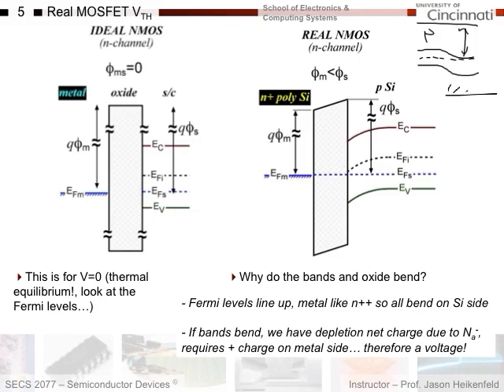if this is the vacuum level up here, and I have n-type semiconductor and then p-type semiconductor, you can see that the distance between the vacuum level and the n-type semiconductor for work function is less than the distance for p-type semiconductor and the vacuum level. So phi sub m is less than phi sub s because the metal in this case is heavily doped n plus silicon. And as you line these things up, this one effectively has to shift up, this has to shift down. And so this goes up, this goes down, and then you get the band bending you see here, okay?